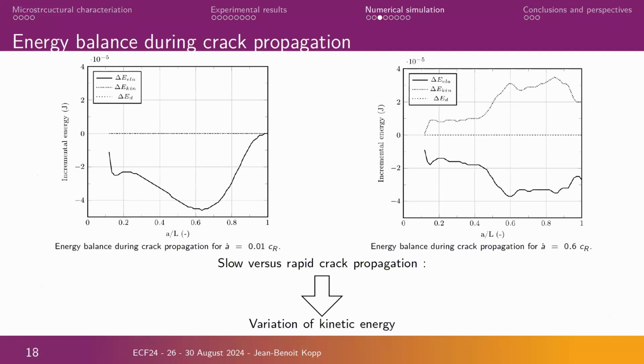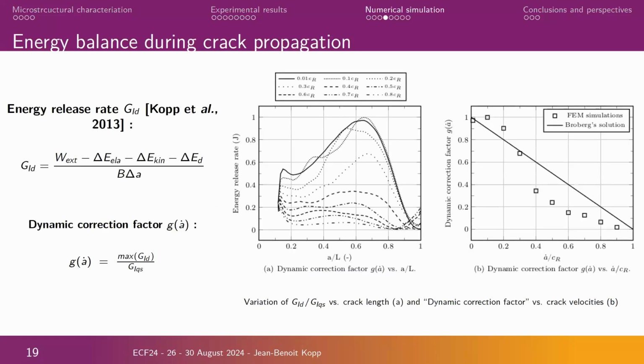The more important thing in dynamic regime is that you have dynamic effects due to the dynamic crack propagation. You have inertial effects and therefore kinetic energy created during the crack propagation. So you have to consider this part of kinetic energy, which is not equal to 0 at this kind of velocity. And by doing that, it is possible to estimate the fracture energy. So finally, we have the fracture energy by making a global energy balance with the different energy parts. And we have to consider a dynamic correction factor to estimate the fracture energy.